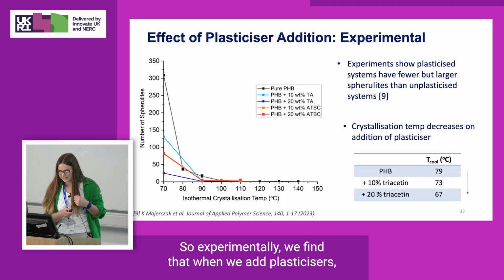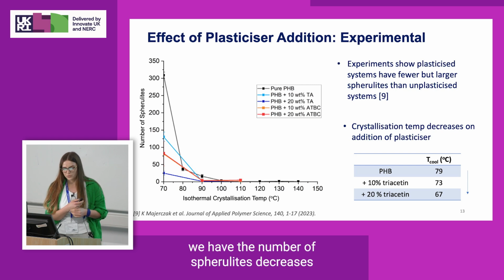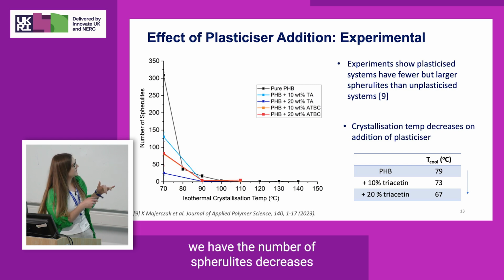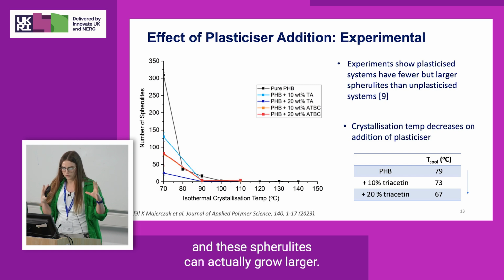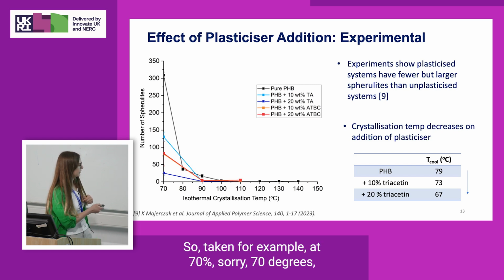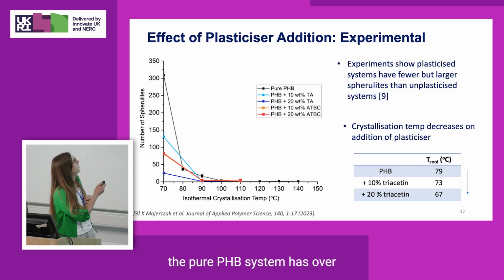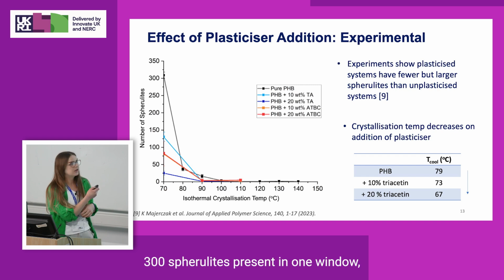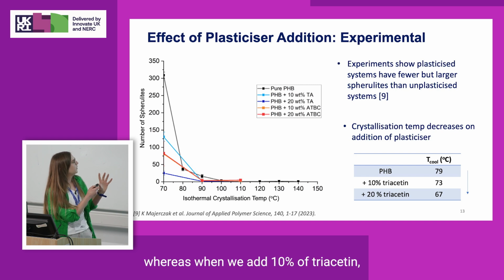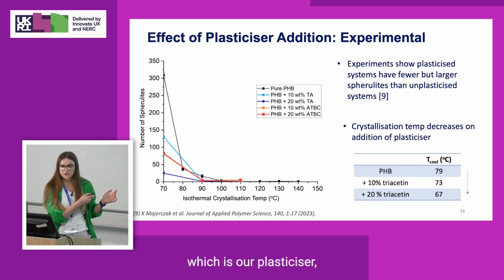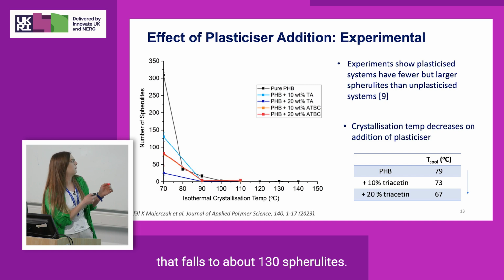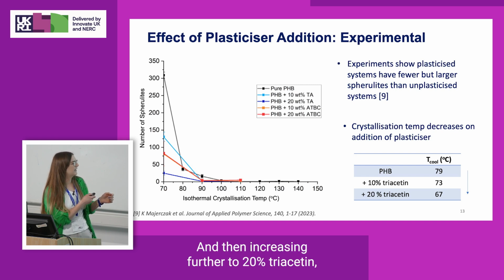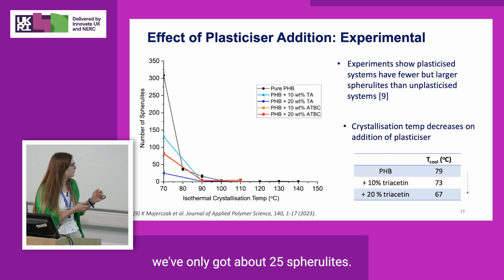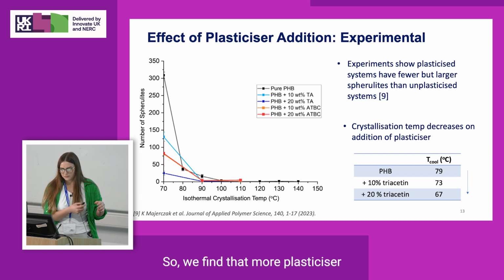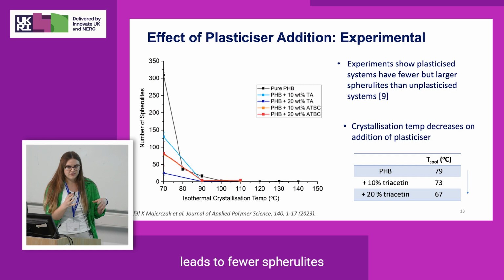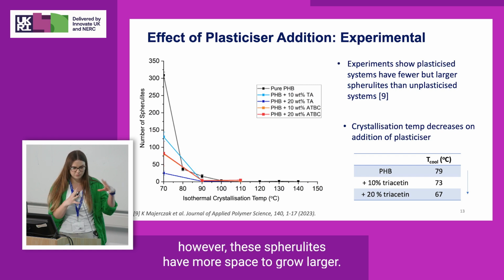Experimentally, we find that when we add plasticizers, the number of spherulites decreases, and these spherulites can actually grow larger. So taken, for example, at 70 degrees, the pure PHB system has over 300 spherulites present in one window, whereas when we add 10% of triacetin, which is our plasticizer, that falls to about 130 spherulites, and then increasing further to 20% triacetin, we've only got about 25 spherulites. So we find that more plasticizer leads to fewer spherulites. However, these spherulites have more space to grow larger.